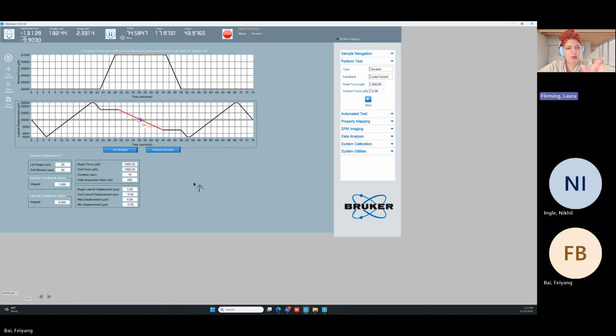And the scratch length here is only 6 microns, so that it's only taking up part of this area. So then we scratch while we're loaded in, then we unload, then we go a little bit further. And then this is again the same. It's very similar to this first one, only now when you're retracing over the scratch, you can see how the normal displacement changed pre versus post scratch. How deep is it? How much material did you take away? Is it constant?